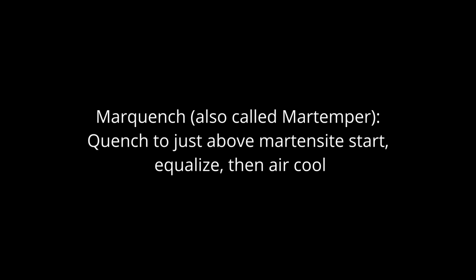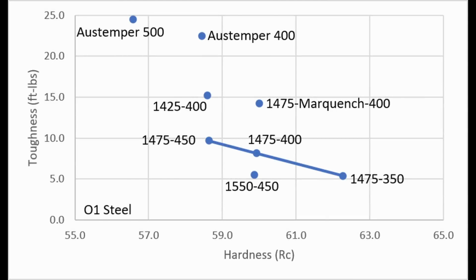And one of the big benefits of that is less warping. Warping usually happens because the surface is cooling faster than the core. But if we mar quench and let everything equalize at a little bit higher temperature first before air cooling, then the cooling is more consistent and it's less likely to change shape. Another benefit is that with that air cooling through the transformation, sometimes the toughness is improved. So if we look at the toughness results, we see that the mar quench indeed did improve the toughness.